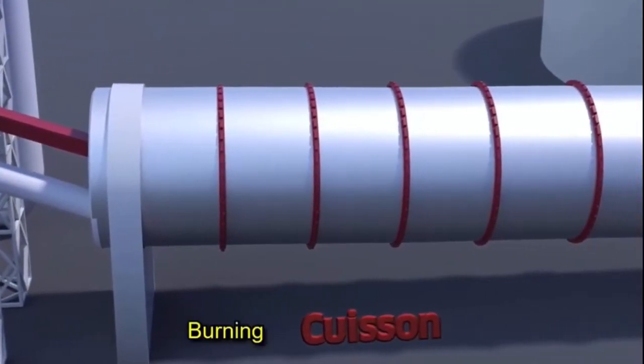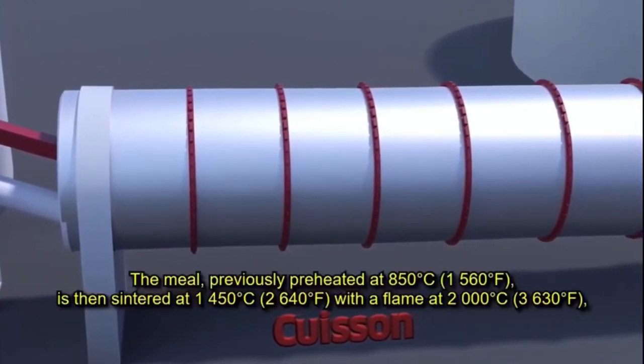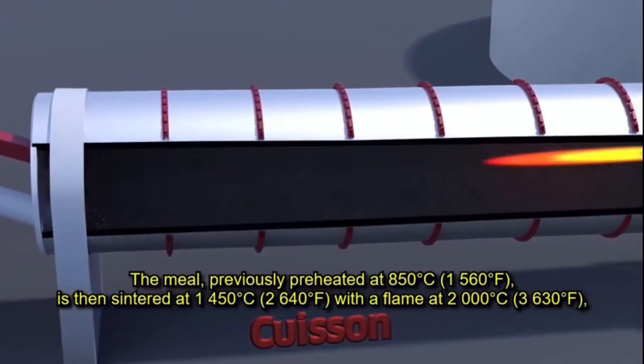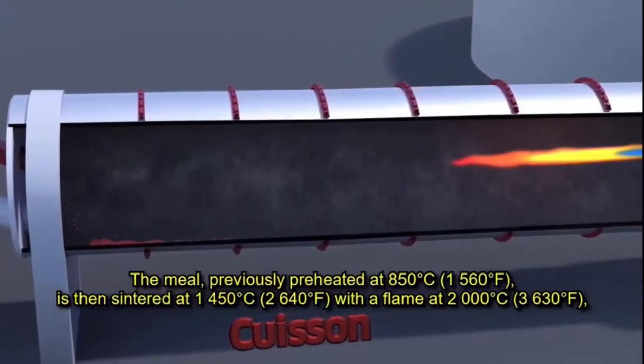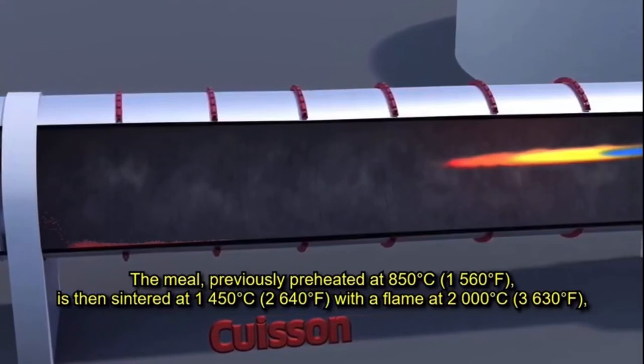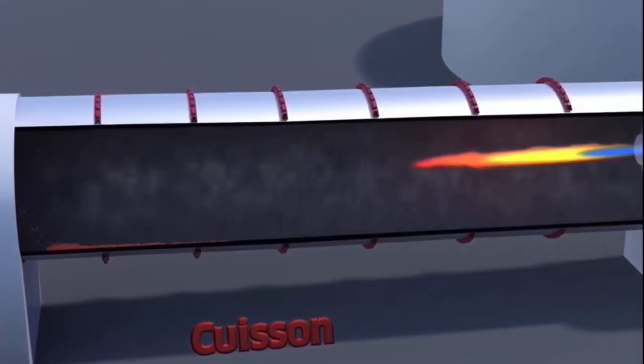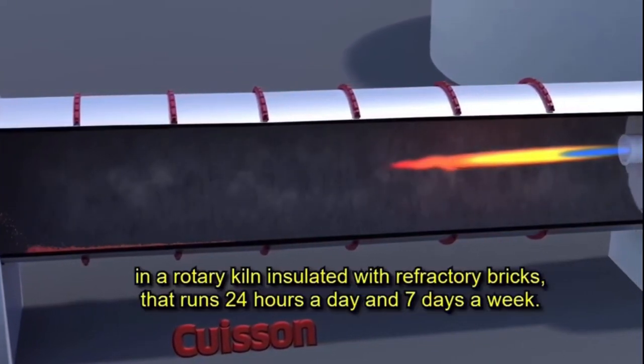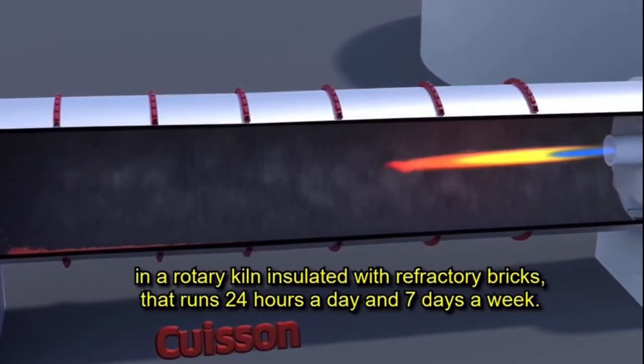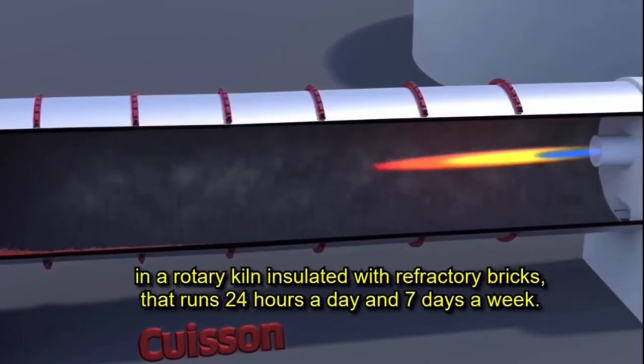Burning. The meal, previously preheated at 850 centigrade, is then sintered at 1450 centigrade with a flame at 2000 centigrade in a rotary kiln insulated with refractory bricks that runs 24 hours a day and 7 days a week.